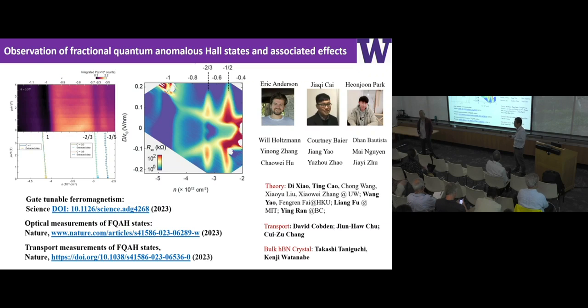But I can tell you what I think is happening: there's a very strong spin-orbit coupling induced splitting in the hole band. It's about 200 meV. But for the conduction band, the spin-orbit coupling is very weak, about 30 meV or even less. So that might be the reason.